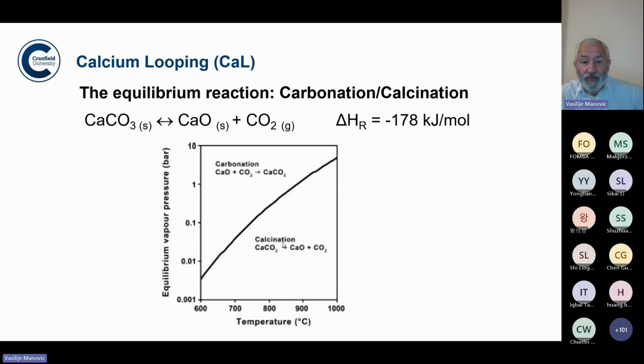When considering calcination, we want a gas containing, say, approximately 95% CO2, and if you look, the minimum temperature must be somewhere here, which is 850, from the thermodynamic point of view. But from the point of view of kinetics of chemical reactions and the intensity of the process, we usually go up to 900 centigrades. We run the sorbent regeneration reaction, which we call calcination.